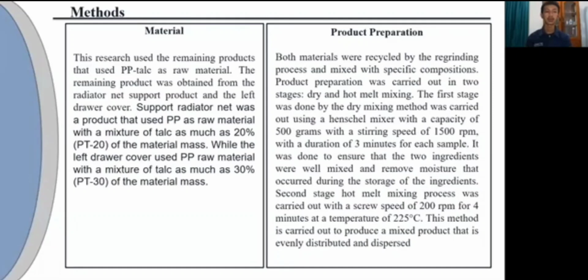Method. Material. This research used the remaining product that uses PP talc as raw material. The remaining product was obtained from the radiator net support product and the left drawer cover. Support radiator net was a product that used PP as raw material with a mixture of talc as much as 20% or PT20 of the material mass. While the left drawer cover uses PP raw material with a mixture of talc as much as 30% or PT-30 of the material mass.